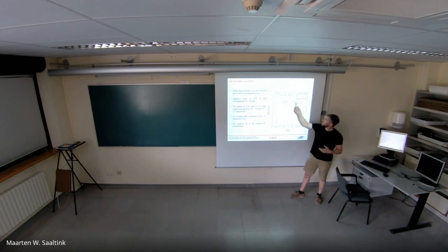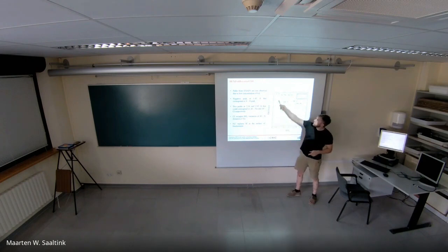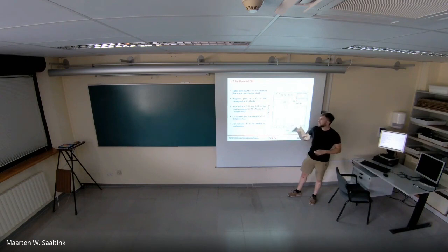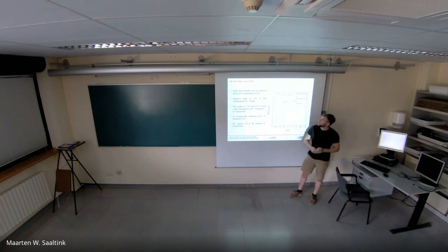it masks the information. But for example, we see a negative peak here, which means that our reacted sample has a lesser amount of the sulfur-oxygen path. This means that our sample has released sulfate. I mean, the reacted basaluminite has released sulfate into solution. This is a consequence of aging at higher pH of this mineral.